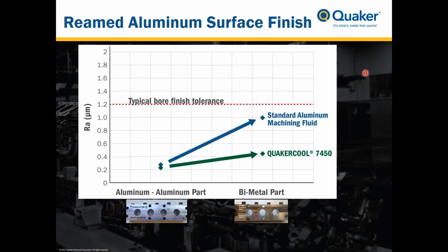And look at the surface finish, the same comparison. Here we have a graph showing the aluminum surface finish after reaming. It shows the bore finish tolerance right up at 1.2, and on the y-axis is the Ra of the ream surface measured in microns, and first is the ream finish with an aluminum part. And here you can see that both of the fluids, the standard aluminum machining fluid that we used and the newer developed fluid, QUAKERCOOL 7450, both are highly effective in giving good finish on the aluminum part. And that wasn't surprising, and that was expected.